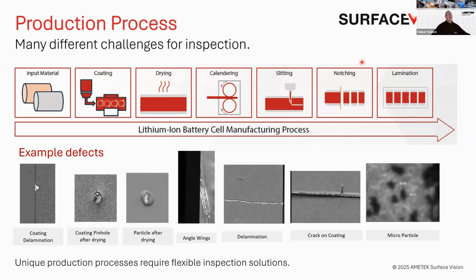And then on the notching area, it really matters also what type of technology is used here. Is it a laser cut notching or mechanical notching? You can enter different type of defects. So the last image, what you see here are particles, which matters when you do, for example, laser cutting on the notching part, where the heat zone where you cut is like a small welding process. Particles can jump again on the coated material and stick out.